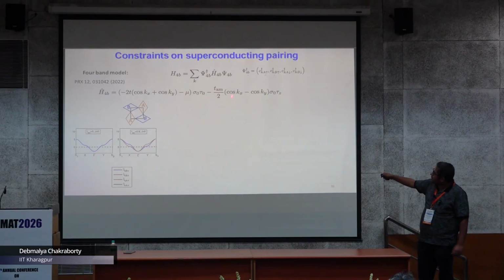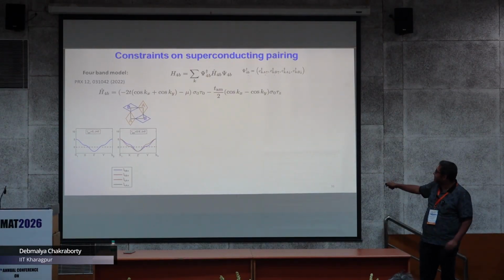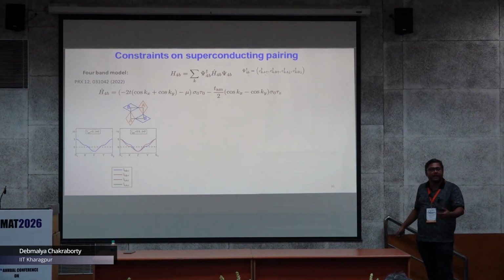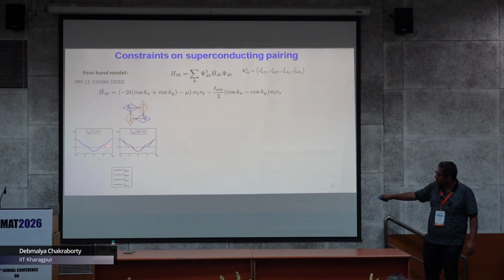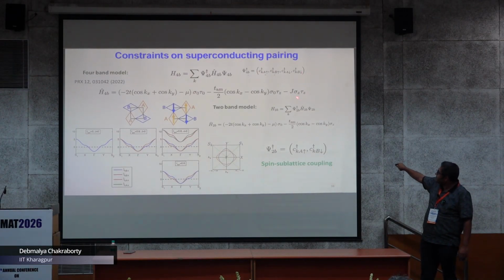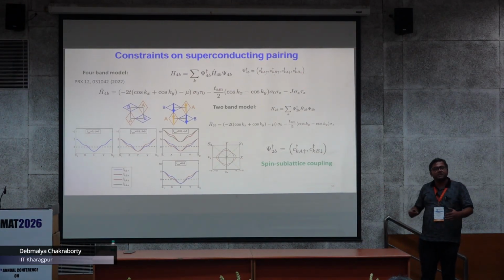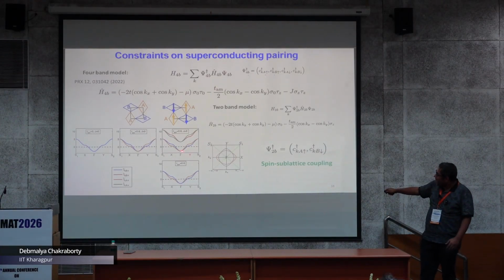Now let me introduce a term like t_M, where I introduce sigma, which is spin, and tau, which is sublattice, a tau z in the sublattice. That means I break the sublattice symmetry between A and B. Still I have spin degeneracy, so I get this band structure. Additionally, if I put a sigma z and tau z, that means another exchange interaction, I see that there are 4 bands, and at low energy near the Fermi level, I have this Fermi surface, and effectively I can consider a 2-band model.